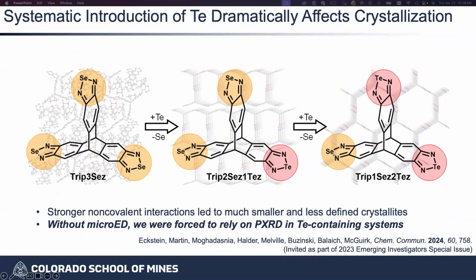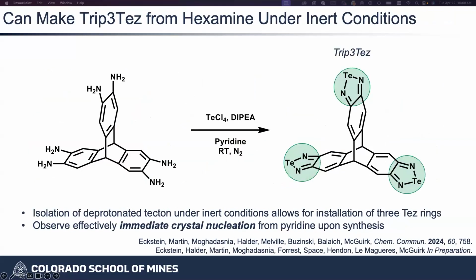And at the time, we weren't really aware of what microED was bringing to the table. And so we published a paper that was single crystal and PXRD. We didn't use microED, and that was our own fault, really. Because the powder looks nice, but we don't have those atomic level structures. But all of that journey led us to finally figuring out how to do the synthesis. We had to isolate this super hot, electron-rich tritelluride system. It just had to be really rigorously air-free chemistry, and then we were able to make this TRIP3 Te.